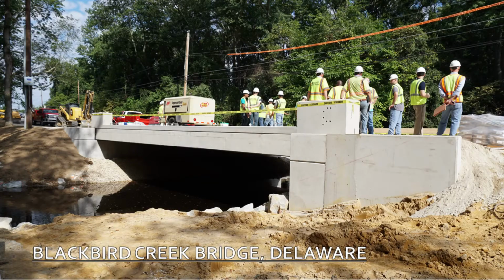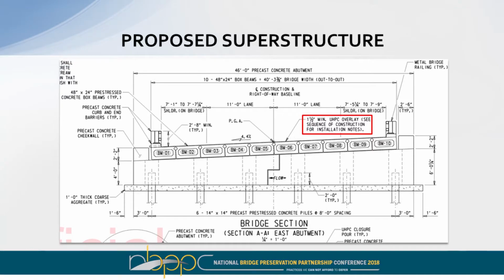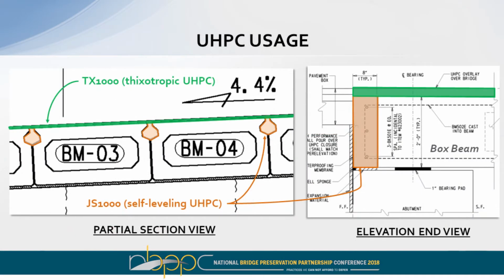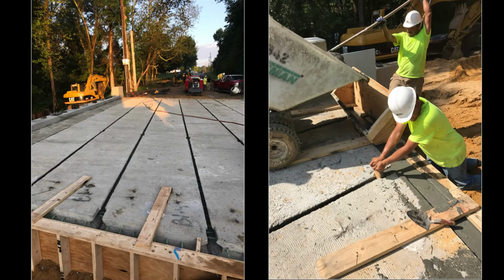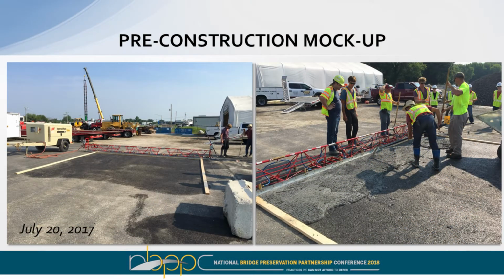So another job in Delaware, this was the second one, a little bit of a different situation. We had an adjacent box beam system, actually a new superstructure where they were using UHPC both in the joints to connect the boxes together and then as an overlay to kind of give an impregnable seal to the box system. And they also used it at the ends of the beams to cap everything. So a couple photos from this, you can see the box beams there and them filling up the ends of the beams with our self-leveling version. And then we did a pre-construction mock-up with the contractor on this, which we highly recommend if the contractor has never done a UHPC overlay work before, because it does behave a little bit differently than what they're likely used to. And here's a little video of that mock-up showing.